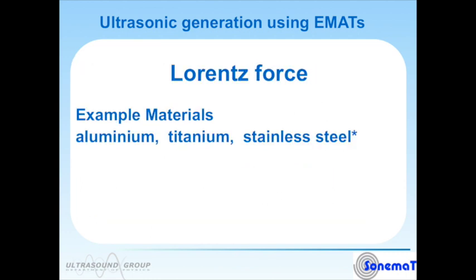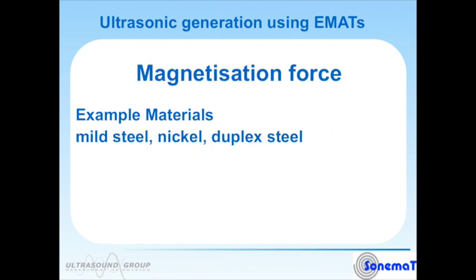So, samples that we typically consider when we're discussing the Lorentz force are aluminium, titanium, and most types of stainless steel. The reason that stainless steel has an asterisk by it there is because magnetic stainless steel does exist, and where that steel is magnetic, it has a potential for other mechanisms such as magnetization or magnetostriction. The magnetization force, well, this is a phenomenon that can occur on magnetic materials such as steel or iron, nickel or duplex steel.